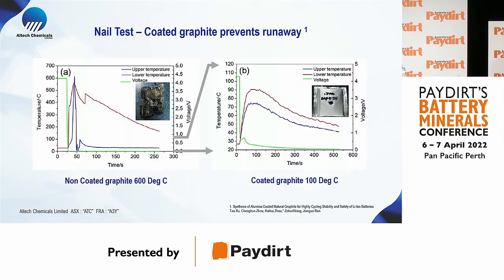I mentioned thermal runaway. Here's a test that shows, on the left-hand side, non-coated graphite batteries. And you can see they do a nail penetration test for safety tests. You can see in the picture there, the battery virtually catches fire from thermal runaway. Temperature soars to about 600 degrees. On the right-hand side is a coated graphite battery, and you can see the battery still intact, and the temperature rises to only 90 degrees.